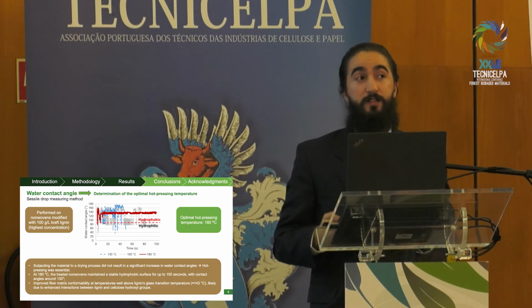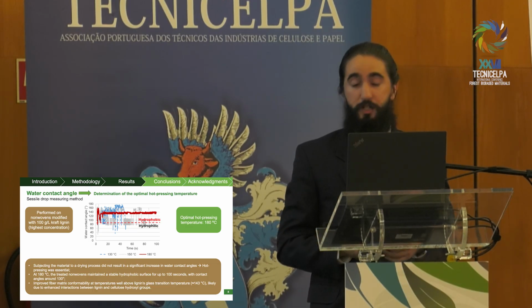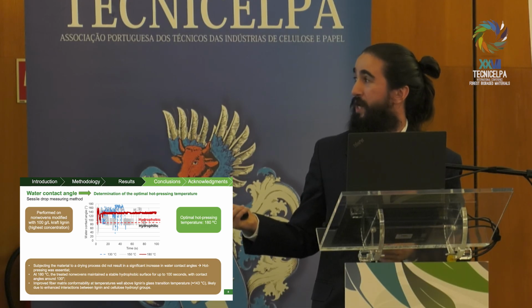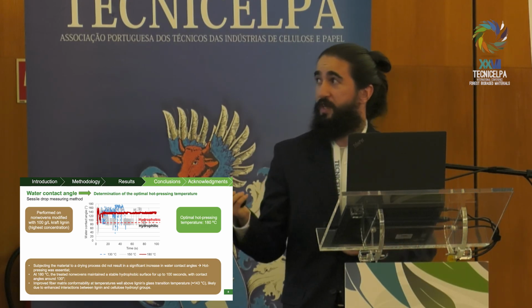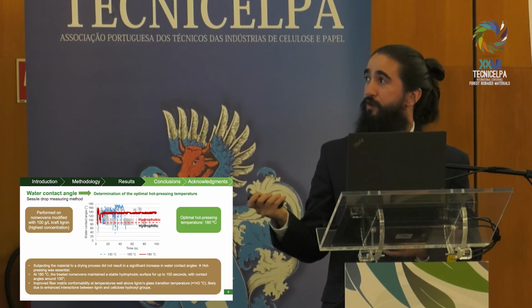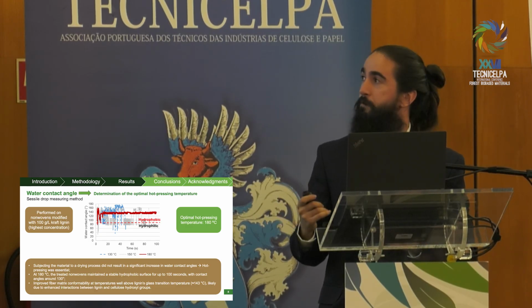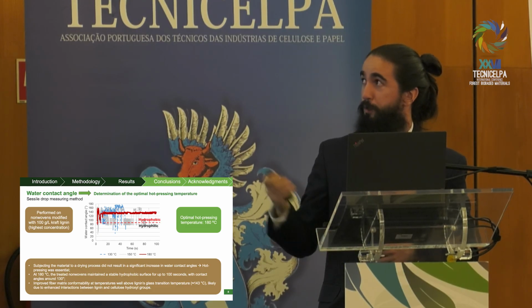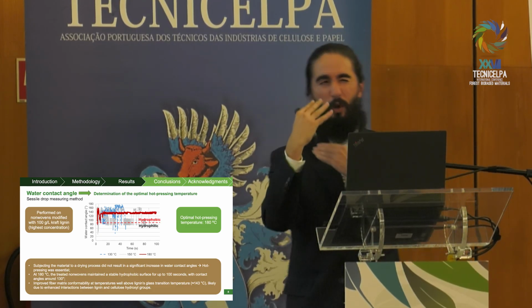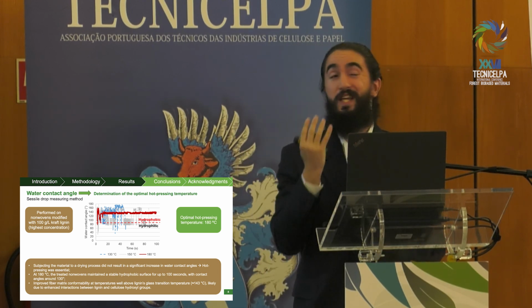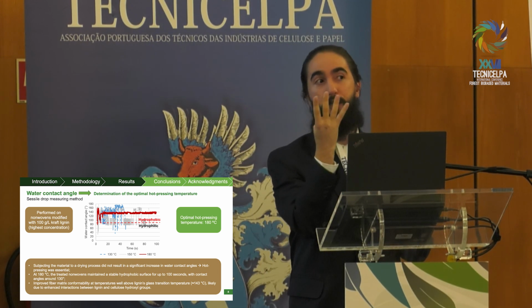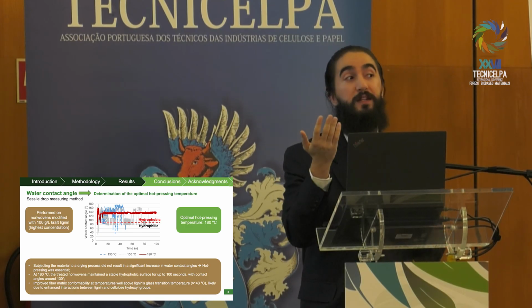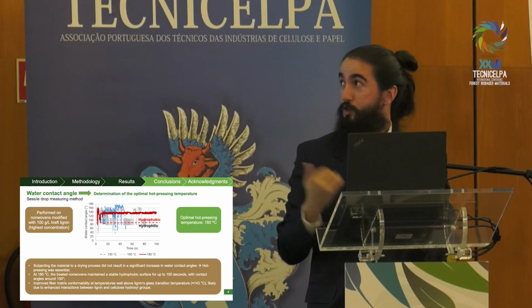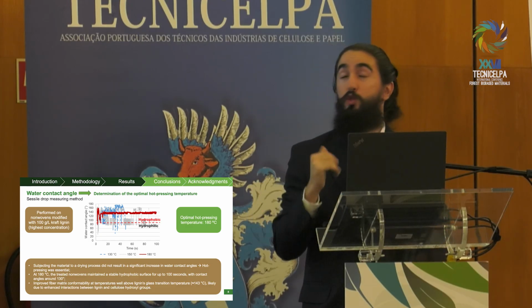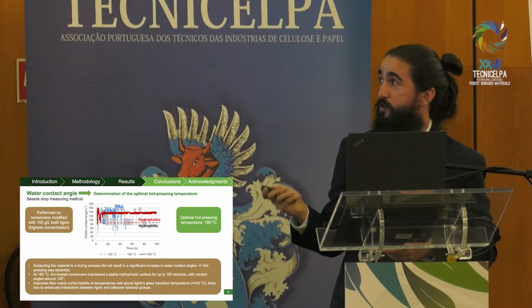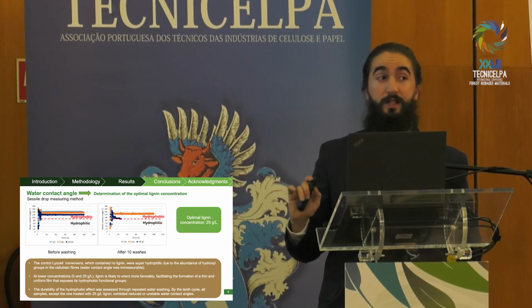Well, we believe that it's due to the lignin glass transition temperature. We assessed using DSC, and it was around 143, 145. So clearly 130 was below, 150 was slightly above, but it might not still provide the property we wanted. And with 180, you have the compression at 2 bar of the hot press with the heating, which means that the bondings between the hydroxyl groups of the cellulose fibers will interact better with the lignin because it's more malleable, so providing a hydrophobic, uniform surface on our material. So according to our results, 180 degrees seems to be the optimal temperature.